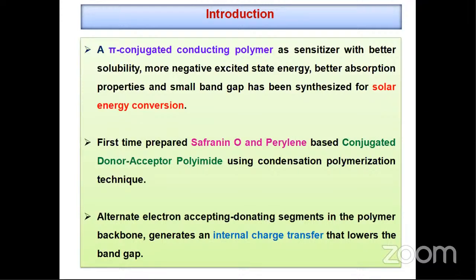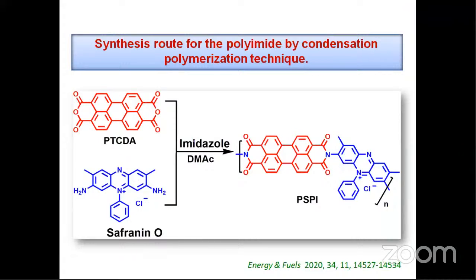So the aim of my work is to synthesize a conjugated conducting polymer with better solubility, better absorption property, and small band gap. For this purpose, I have reported for the first time the synthesis of safranine and perylene-based conjugated donor-acceptor polyimide using a condensation polymerization technique. This design, using a conjugated polyimide containing alternate electron accepting and electron donating segments in the polymer backbone, generates an internal charge transfer that lowers the band gap of the polymer, and as a result, this conjugated polyimide absorbs at longer wavelength. This is the synthetic route for the synthesis of the polymer.